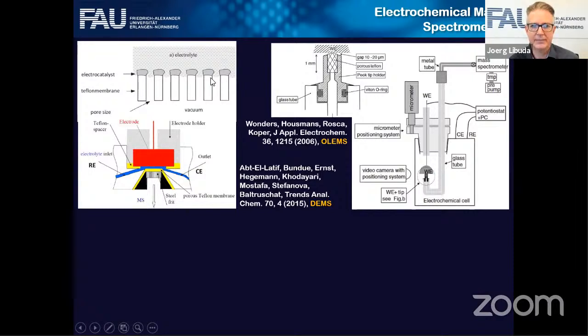So you have a porous hydrophobic membrane, and then you can put the electrocatalyst on this membrane. Now, this is very efficient. The products here in the electrolyte may evaporate into the gas phase here, and in the vacuum, you can detect them by mass spectrometer. Very efficient, very successful experiment. However, this type of experiment is not compatible with the single crystal that you make in ultra high vacuum.